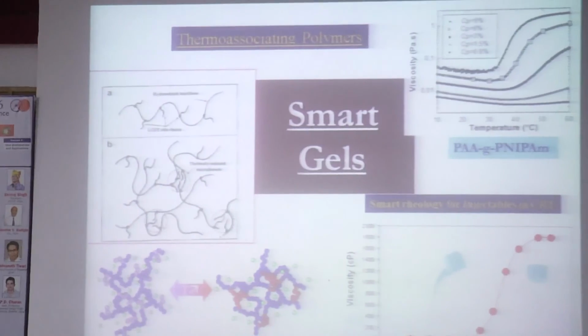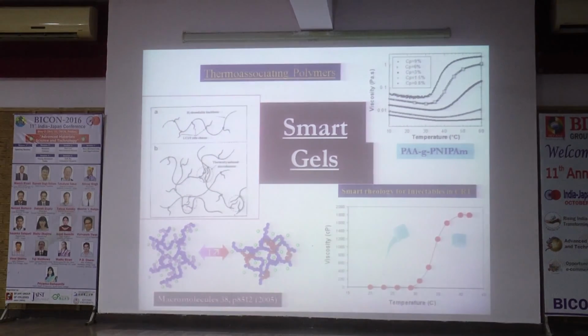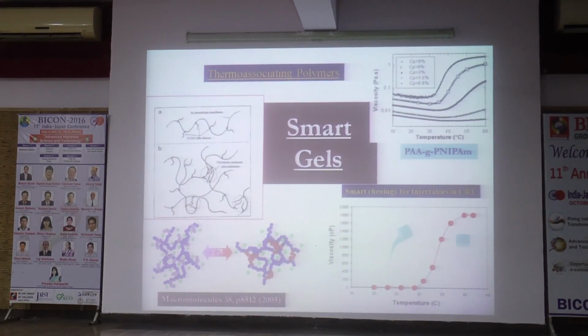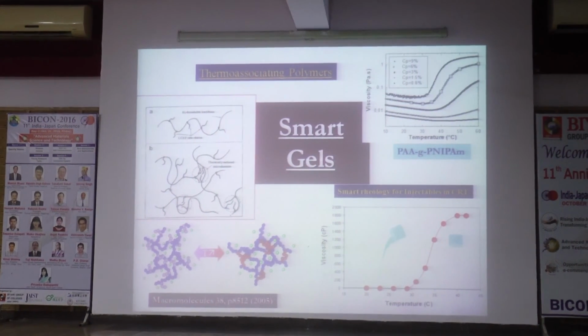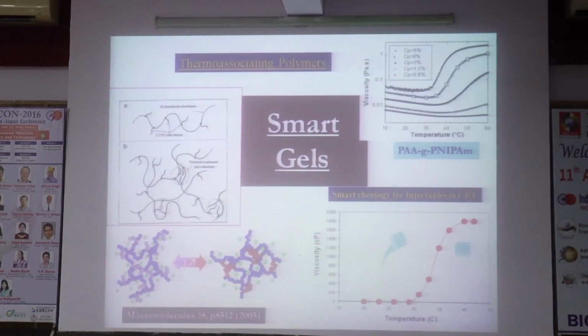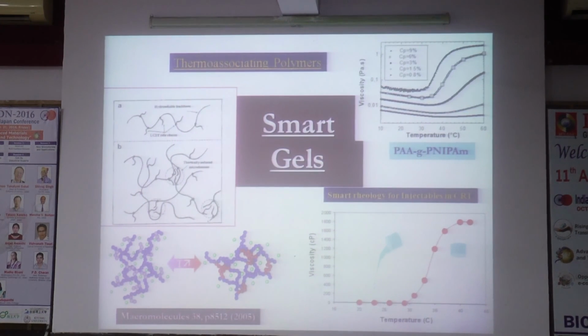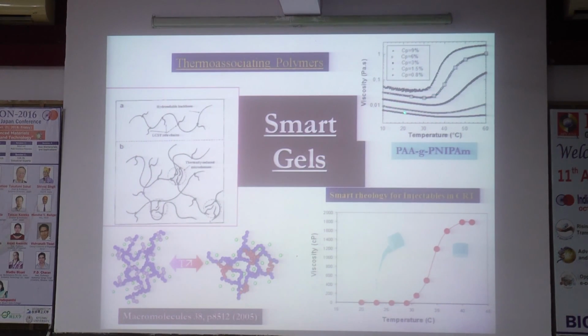And if we want to use this polymer to make a smart polymer, what we have done is that we take this polymer and functionalize it. For example, in my next slide I will show you. If you take this polymer and attach it to any water-soluble polymer. For example, you take polyacrylic acid, you take polyvinyl alcohol, you take a carboxymethyl cellulose. If you attach LCST polymer to that, it behaves like a thermoassociating polymer. That means it doesn't undergo phase separation, but it undergoes from liquid to gel state by increasing the temperature. For example, here you can see it's a liquid here. By heating, it forms a gel.